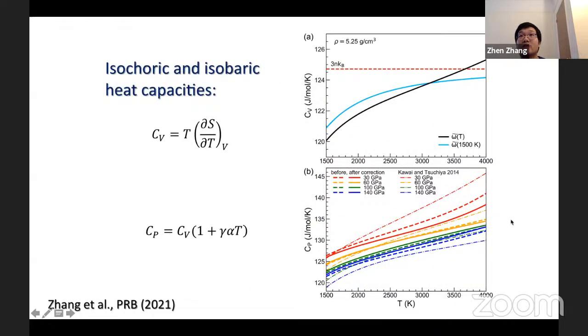Here are the obtained isochoric and isobaric heat capacities. For the isochoric heat capacity, 3nk_B is both the Dulong-Petit classical limit and the high temperature limit within the Debye model for harmonic crystal with temperature independent phonon frequencies. Here, by using the frequencies solely obtained at 1500 Kelvin, CV converges to such limit. However, by using the temperature-dependent phonon spectra, the obtained CV can be higher than such limit at high temperatures. This is another indicator of anharmonic effects. The obtained isobaric heat capacity can be used to obtain thermal conductivity for experimentalists.